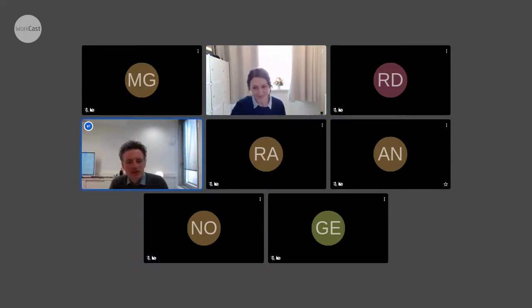Between liquid cells and solid state cells? No, sorry, lithium and sodium cells. But with liquid electrolyte, I guess. Yeah. That's of course a very long story, I cannot completely answer this. The SEI formation is not the same, because you have different conductive salts and a different redox potential where you intercalate your ions, lithium or sodium. What is the same is the solvent, or you can choose to take the same solvents.